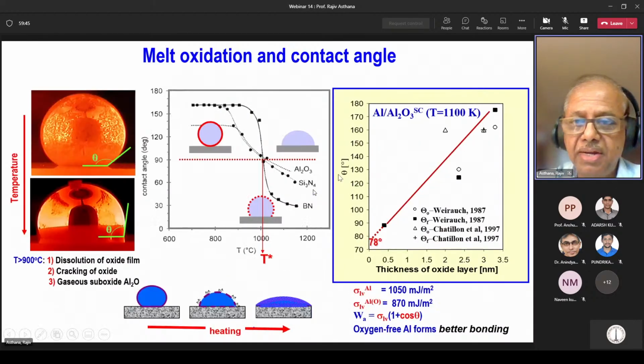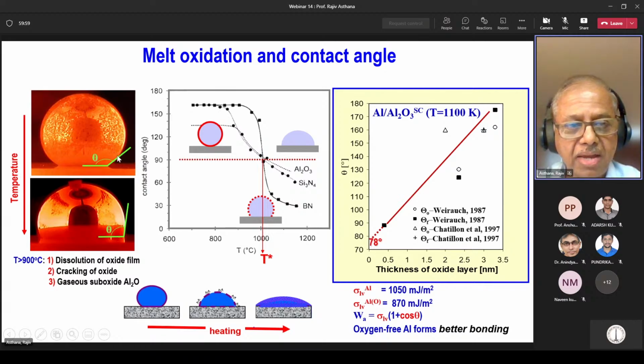And if you look at the data on different substrates, here we're looking at pure aluminum droplets spreading on aluminum oxide, silicon nitride, boron nitride at different temperatures. And we are plotting the equilibrium contact angle. That means the angle when the droplet has stabilized its shape. So when you look at the data, pretty much in all substrates, there is one temperature close to 1000 degrees Celsius where the contact angles are all the same. So the angle does not depend on the substrate up until this temperature.